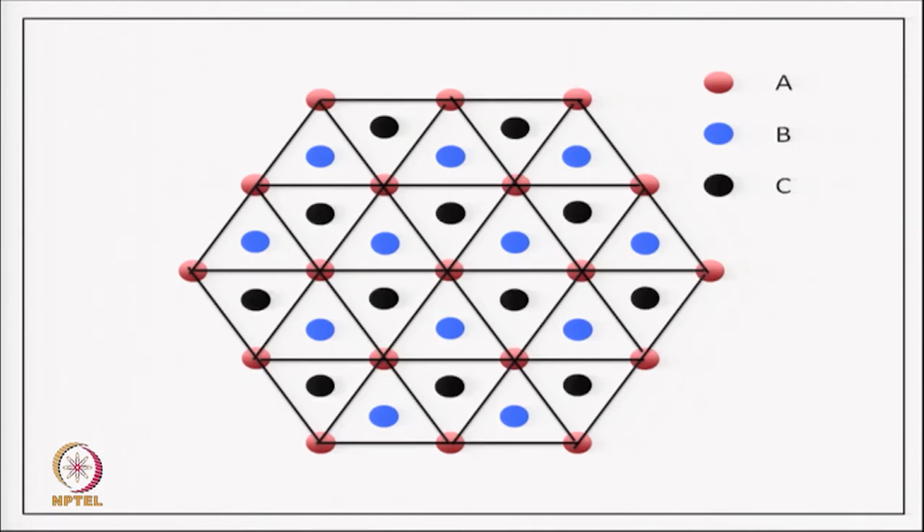So, if I fill all these sites, I get an exactly identical close packed layer, but shifted at the third layer. And then if I continue this sequence ABC, ABC, I get a crystal structure which we now wish to analyze in terms of lattice and motif.